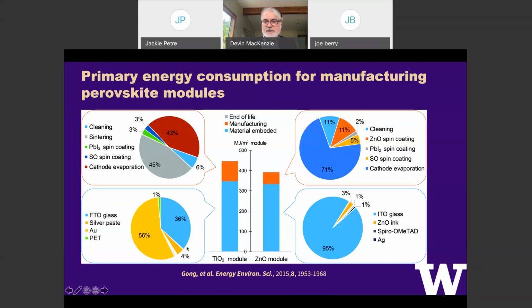That's also an energy and investment. But this is not going to use gold. We're going to use copper, whatever. Still, cathode evaporation is a huge fraction of the manufacturing energy consumption to produce PV. And look at energy devices, the majority of it, and the majority of that is just about the glass. It's about the ITO glass. That's where all the energy is. So those are challenges, barrier properties, and this immense embedded energy related to the glass.